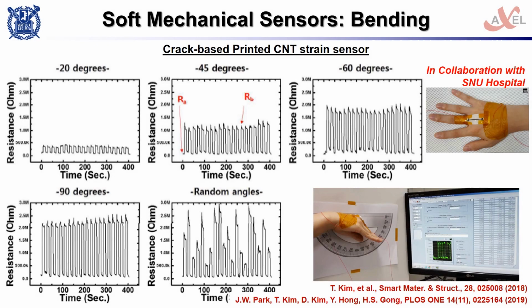We can also use CNT as the sensing material. This result shows an example of a finger joint rehabilitation monitoring system. We used the CNT material as a resistive bending sensor material, and we also incorporated a crack generation mechanism into the CNT-based strain sensor.